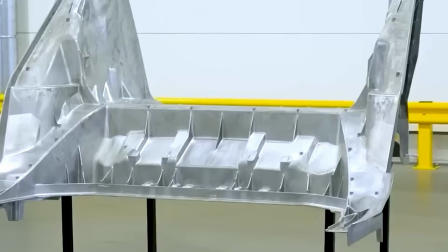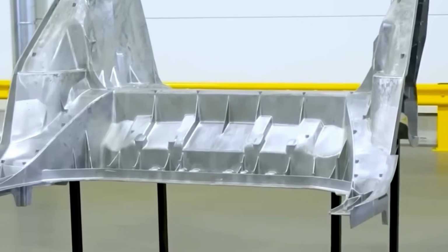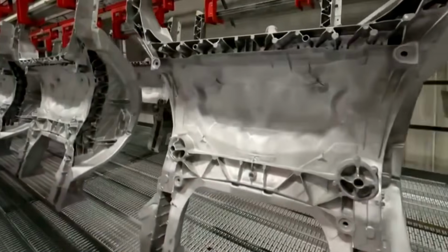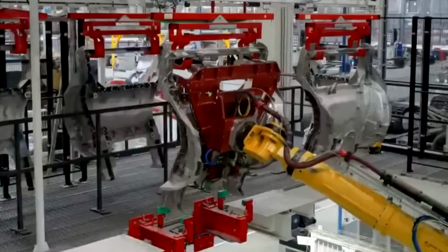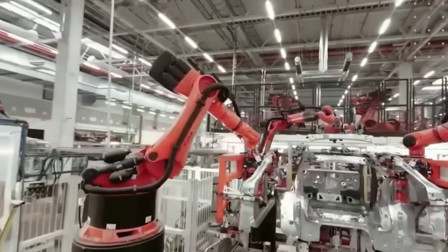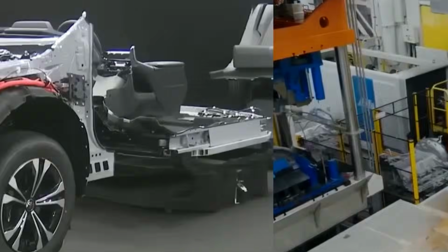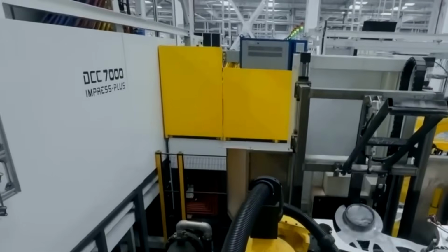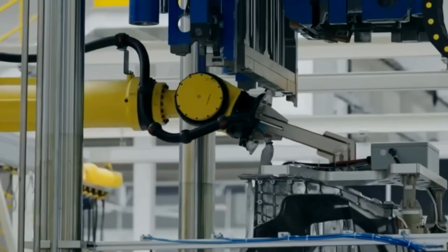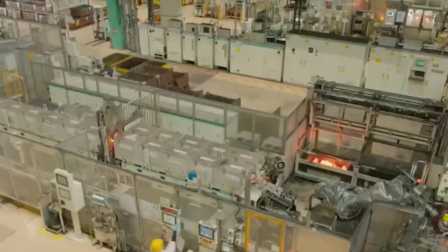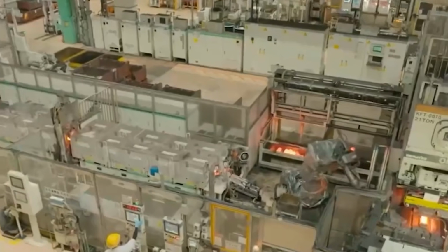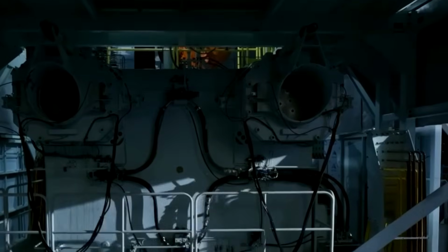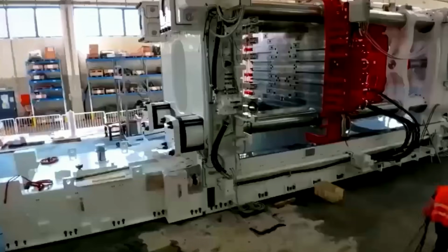A plunger, lubricated with approximately 8 milliliters of oil before each shot, drives the metal into the die cavity with enormous force. After injection, the metal solidifies inside the die, and the red-hot casting is extracted at a temperature of around 400 degrees Celsius. It is immediately submerged in a cooling bath, where the temperature drops to approximately 50 degrees.